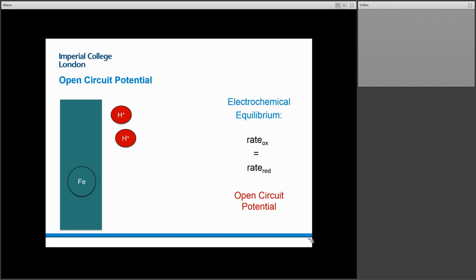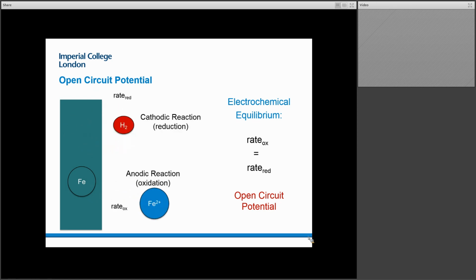So with that, I'm going to jump right in and talk about the crux, if you will, of our electrochemical measurement, and that's open circuit potential. So when we have a metal, in this case I've shown iron because it's one of our favorite things, we have an oxidation reaction where the iron 2+ is released into solution and the electrons can then be subsequently reduced as part of the cathodic reaction. So I've shown the two here, each modeled with one individual reaction. At the point in which the rate of oxidation and the rate of reduction are equal, we call it an electrochemical equilibrium. And that is the point at which we would say we are at our open circuit potential.